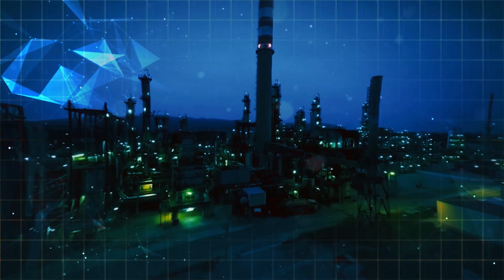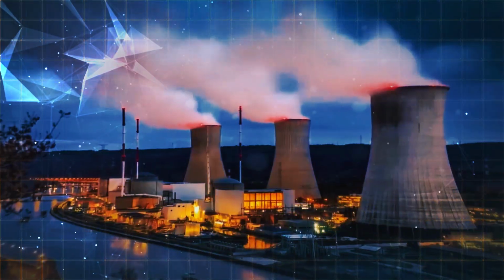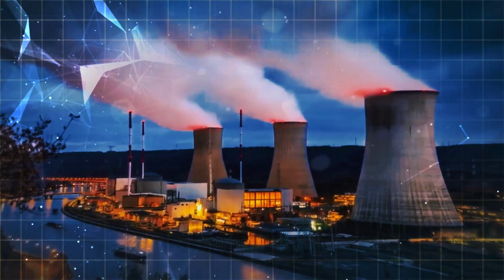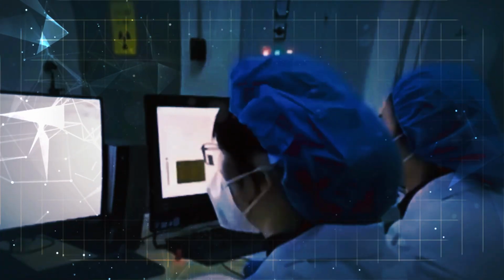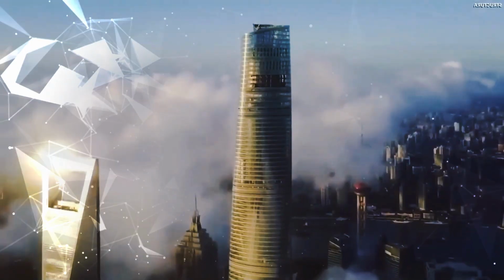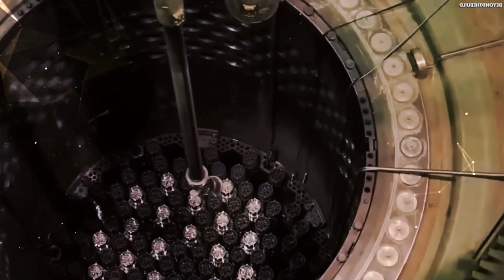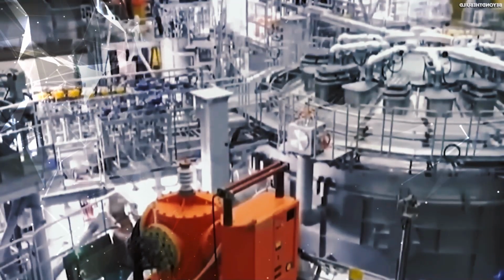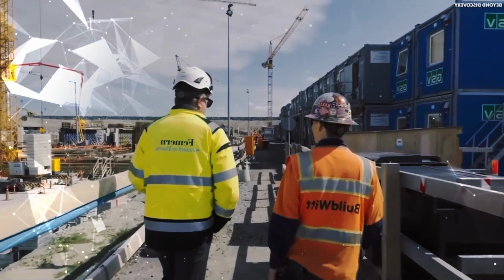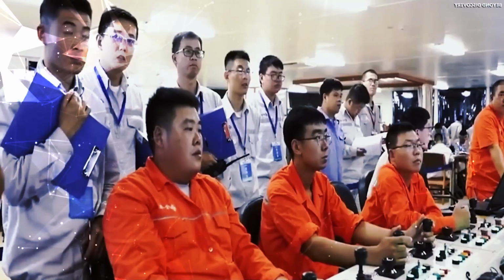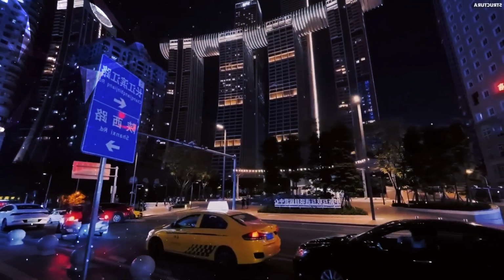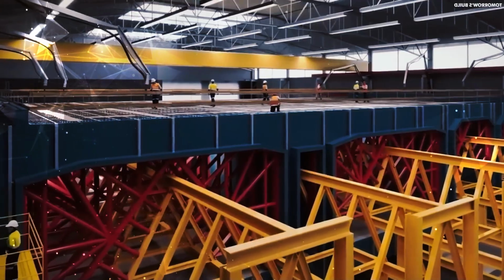For the reactor's graphite moderator, instead of blocks, engineers filled the core with 60,000 graphite spheres coated with silicon carbide, each about the size of a tennis ball. Molten salt flows between them, creating a naturally self-regulating neutron environment. When the temperature rises, the salt expands, reduces neutron absorption, and slows the reaction without the need for control rods. In addition, a frozen safety plug melts if overheating occurs and drains the fuel into underground tanks. This design makes a core meltdown physically impossible.